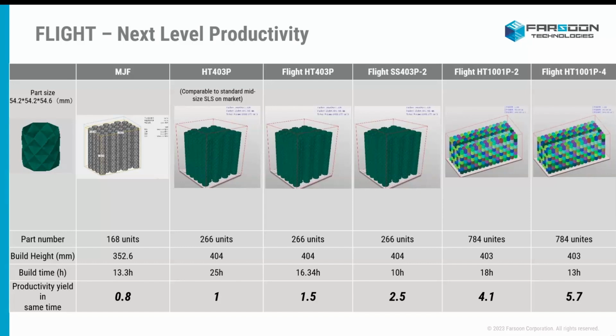And that's where our single fiber laser system comes into play. We're able to cut down the build time to a little over 16 hours for 266 parts. That gives us 1.5 times the productivity yield in just about the same amount of time as the MJF system.